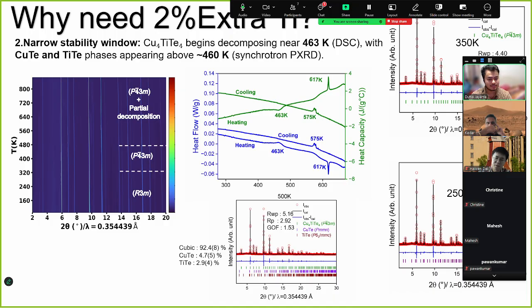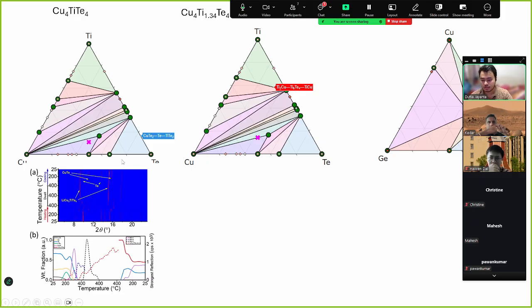Synthesizing using DJS, the cooling is very fast. Even if you saw this paper, they actually formed the copper 4 titanium telluride, but when they cool down below 400 degrees, the phases started to decompose. This copper telluride is forming, so you cannot avoid it using slow cooling or any other way.